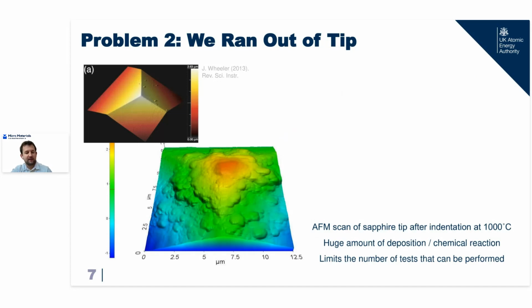In fact, more problematic is what happens to your tip. So these are AFM scans of a pristine Berkovich from the literature, and what happened to our indenter after 4 indents at 1000 degrees. And this is enough to take the measured hardness from half a GPa up to 4 GPa. It's basically ruined. It's turned into this horrible blob, and means each indent costs about £800, I think, from memory, which is not very cost-efficient testing.